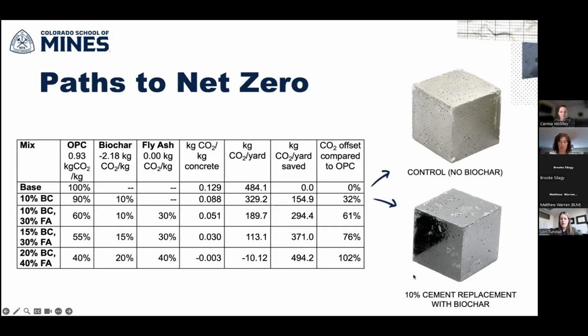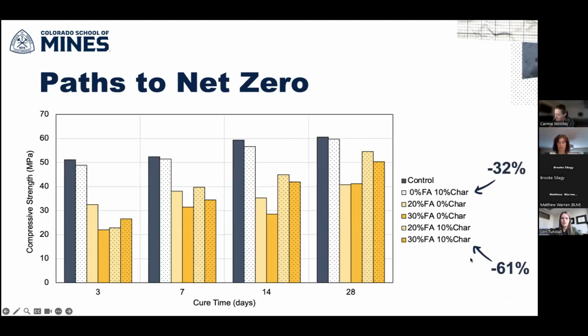And so if you look at this bottom row here, this is just one potential path forward. So say we can't maybe get to really large replacements of the cement with biochar. But if we partially replace it with biochar and fly ash, then we could get to a carbon negative mix. And like I said, when you include fly ash, you get that lubricating effect. So we anticipate that we won't have the same kind of rheological challenges as just replacing the cement with biochar. However, we'll see how that works out. That's stuff that we haven't explored yet. But I just wanted to indicate a path forward with biochar as part of the solution where we could really feasibly get to carbon neutral or negative.